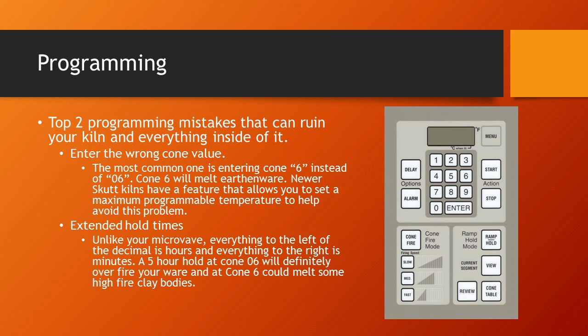Another thing is extended hold time. We always recommend that you put like a 5-minute hold on the end of your cone fire mode, and that's holding at peak temperature, and that allows the kiln time for heavier loaded areas to kind of catch up with the rest of the kiln and all the glazes to flow evenly. But on your microwave, everything to the left of the decimal is hours and everything to the right is minutes. So that could be the mindset of your employee. And if you put 5.00, that would be a 5-hour hold, which is definitely going to cause some problems. So build that into your training.